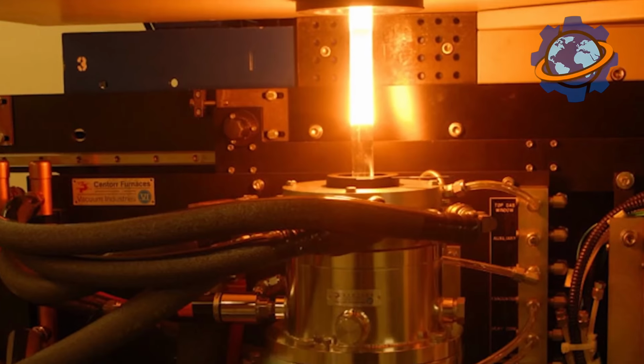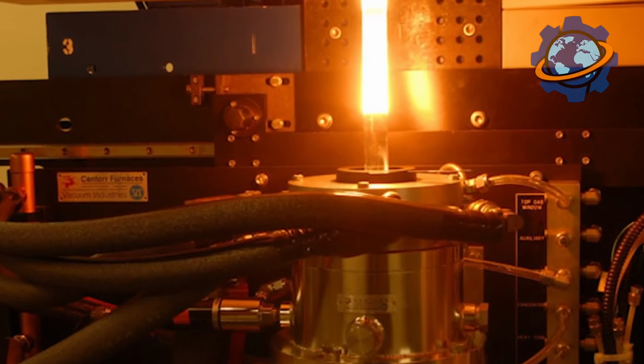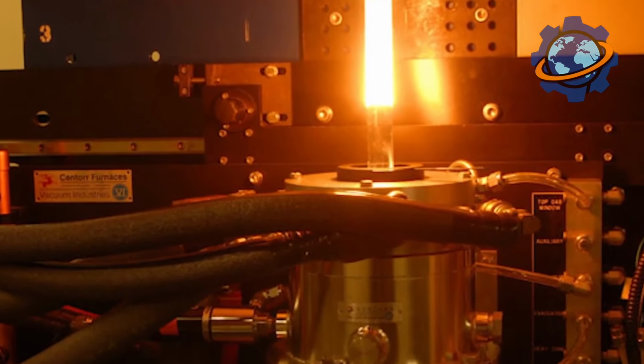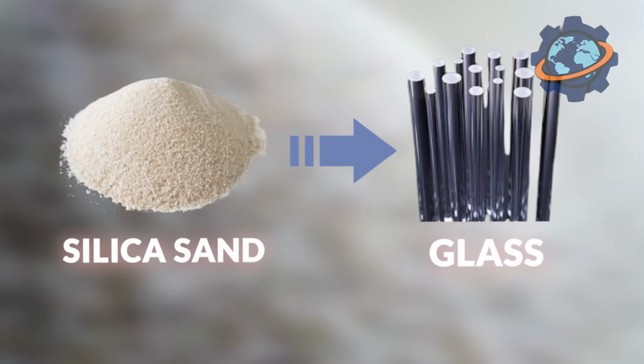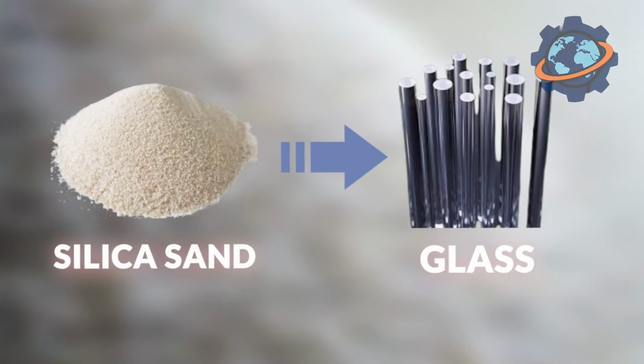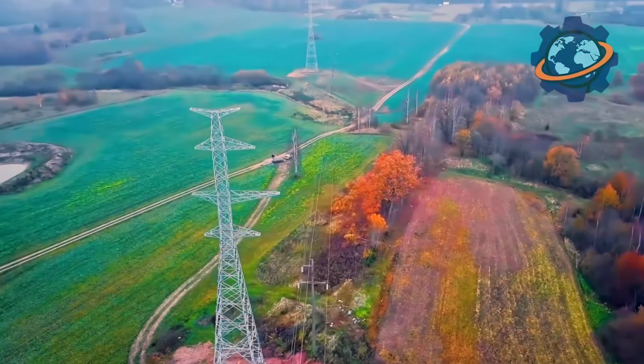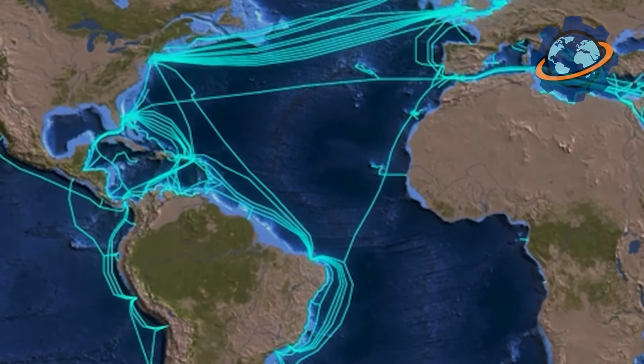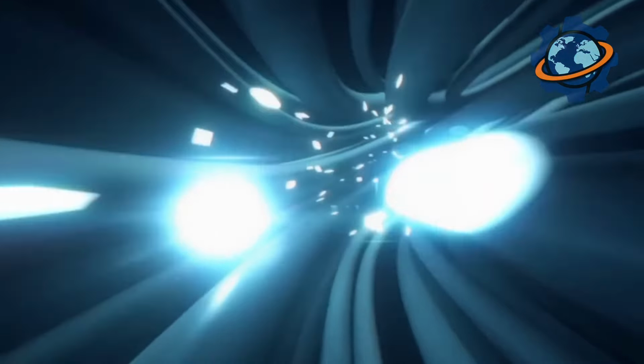Imagine this. In every pound of raw material, no more than a few millionths of an ounce of impurities. And this is critical, because even 1 billionth of an inch of foreign metal or organic matter can cause light scattering or absorption in the fiber optic cable. And then the signal, which was supposed to travel 60 miles without amplification, simply disappears.